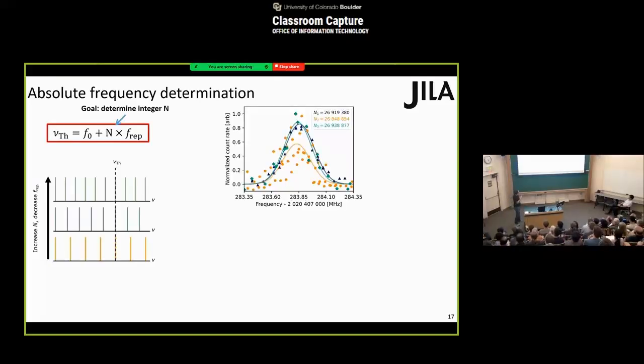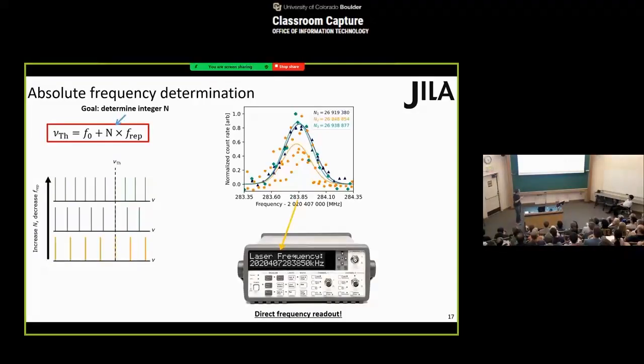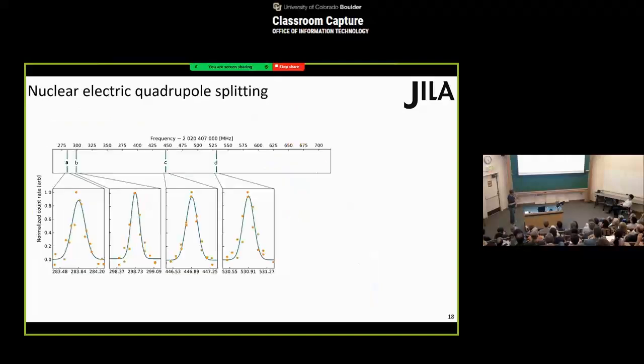So we did that with 3 different measurements, and we can see that once we solve for these integer mode numbers, we can scale the measurements back to optical transition frequencies, where the different measurements of the same transition line indeed agree very well with each other. And the horizontal axis now is essentially a direct readout of the transition optical frequency. So you can see our frequency comb also serves as a frequency counter for us to directly measure optical transition frequencies. Now you saw that we had a couple of different spectroscopy features.